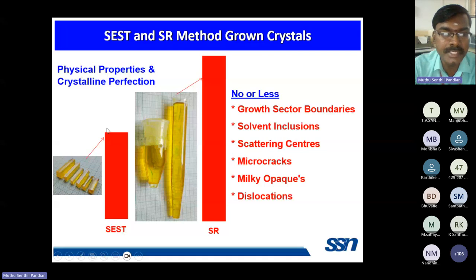So from this observation, one can easily conclude that the growth sector boundaries, solvent inclusions, scattering centers, micro cracks, milky opaques, and a large number of dislocations in the conventional method grown crystal cause the low physical properties and low crystalline perfection. But in the SR method grown crystal, there are no growth sector boundaries, no solvent inclusion, no scattering centers, no micro cracks, no milky opaques, and less dislocation density, which causes higher physical properties like higher optical transmittance, higher mechanical stability, and higher dielectric permittivity. Crystalline perfection we also checked using HR XRD and chemical etching measurement, and we have a very low full width at half maximum, which clearly indicates that the crystalline perfection of the SR method grown crystal is very high compared to the conventional method grown crystal.